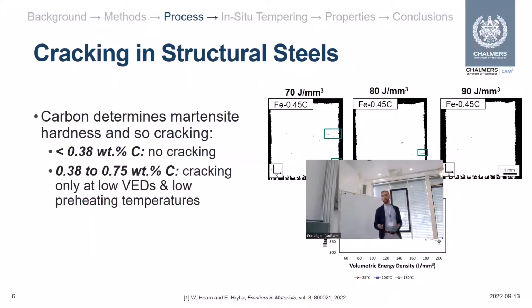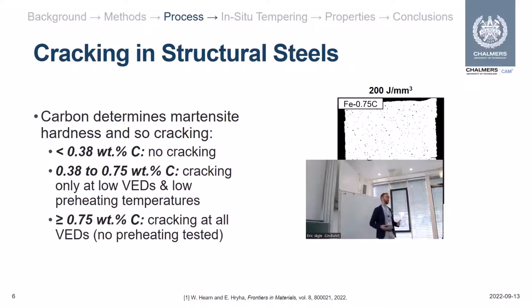And then when you go really high in carbon content, 0.75 weight percent or greater, we didn't look at preheating temperature, but just from the energy input, we couldn't get crack-free specimens. So when you start going really, really high in your carbon content, you need to have a combination of both high energy input and likely high build plate preheating. But what I want to get at here is that very clearly, despite cracking being not prevalent, but present here, you are able to avoid these issues by improving the in-situ tempering of your material.